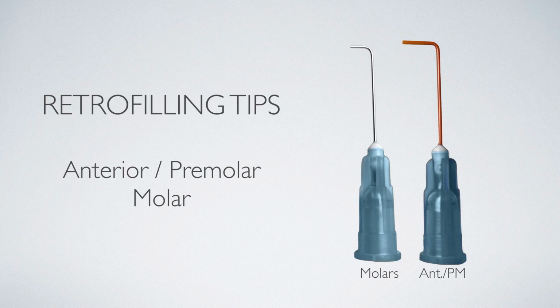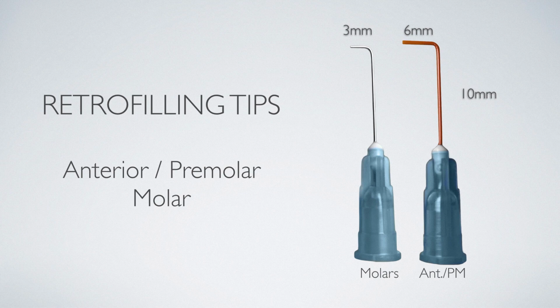And the same thing happens with the tips that we have created. So we have tips that have different diameters and different lengths that allow you to achieve this end, which means no matter what your retro preparation diameter is, you can take the nozzle all the way down to the end and then fill up. These tips come with different lengths, and in fact the plastic tip that is for anteriors and premolars that is 6 millimeters long can actually be trimmed down to much shorter lengths, and so you can custom make the tip to fit exactly the retro preparation that you have. So that is a tremendous gain in efficiency. With that, let's take a quick look at a case where it's been applied.